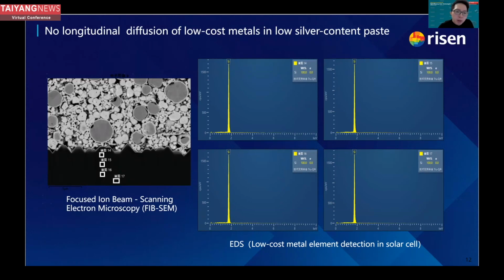And as you can see, we have a 4-point selected. Within all the 4 trends from these 4 pictures, we can see only silicon was detected, no copper was detected, which verifies that we don't see any copper diffusion in the vertical direction in solar cells.